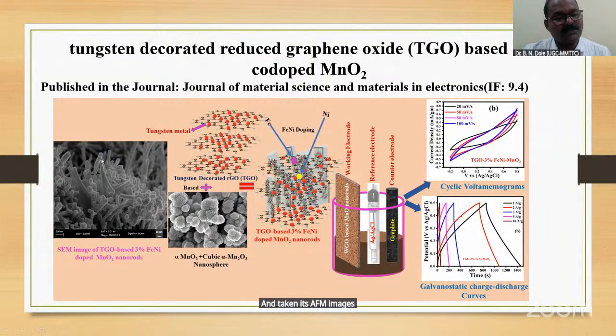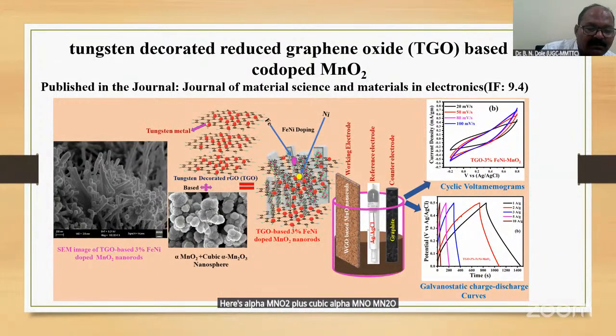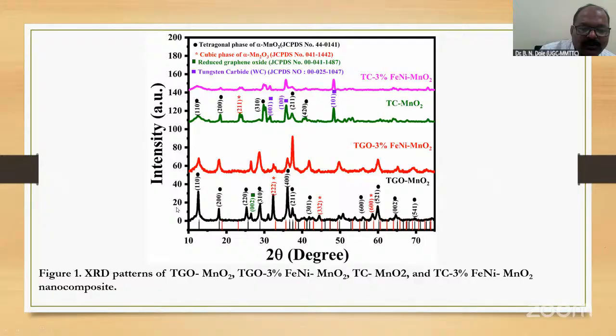See here, very small, but you see the beautiful picture of this TGO, means this is the tungsten, okay? Tungsten decorated RGO. Here see alpha MnO2 plus cubic alpha Mn2O3 nanosphere. Here this is the iron and this is nickel, okay? Iron nickel doping. Tungsten GO based 3% iron nickel doped MnO2. See picture. This is the galvanostatic charge discharge curves. Now you can go through this. See the figure. This is the XRD pattern.